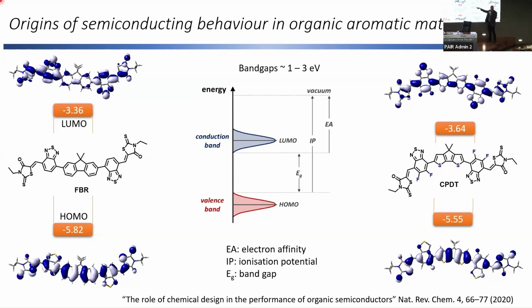So if we just think about a reduction reaction, what are the common reduction reactions? Well, of course, one I just mentioned would be taking an electron with water and forming hydrogen. Another is taking an electron with oxygen and forming a superoxide radical anion. That's a big problem because in combination with water, you form these peroxide or hydroxide radicals, and they chew all these structures up. So if you've got an electron transport material, you typically want to bring the energy level down as much as possible. In other words, increase the electron affinity.